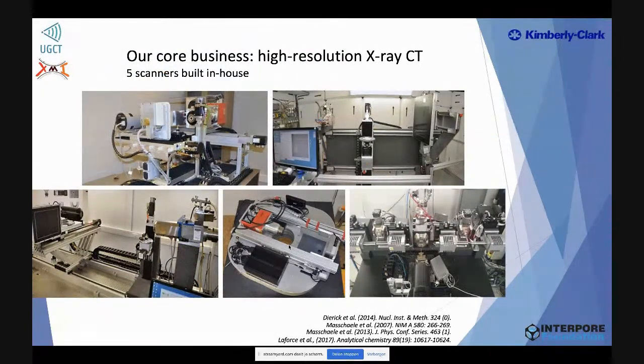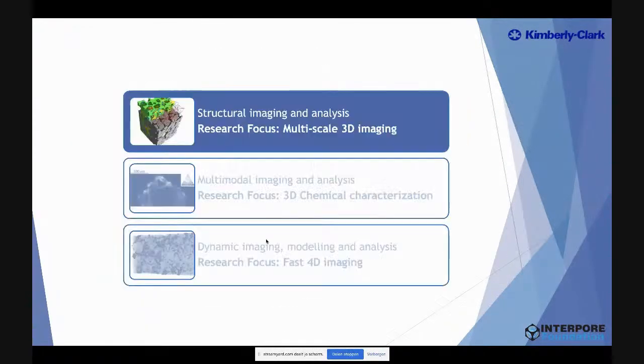We have in the Center for X-ray Tomography of Ghent University several scanners, each with different sources and detectors. Some have X-ray sources with a small focal spot, others with a bigger focal spot, but then able to scan at a higher energy. We have detectors sensitive for high energy, for low energy. So we have this combination because it allows us to always get the optimal image quality needed for what we want to see. And they were all built in-house.